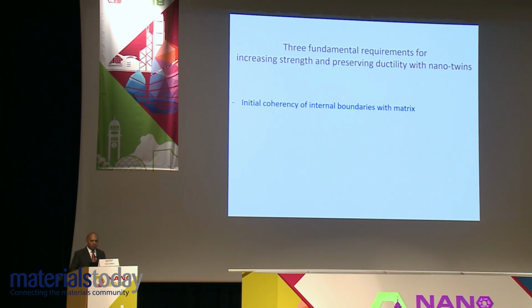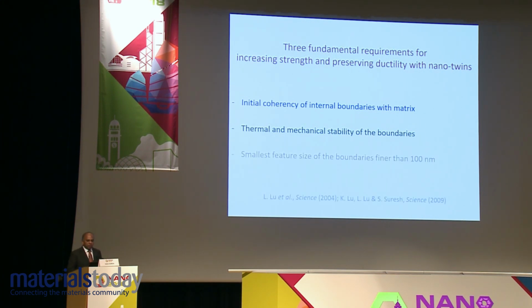What are the requirements? We identified 3 requirements. You need to create internal boundaries that at least have initial coherency, mechanical coherency with the surrounding matrix. You need to have thermal and mechanical stability of the boundaries during mechanical loading, whether it's monotonic loading or cyclic loading, at room temperature or at elevated temperatures. And then in addition to that, there is something unique about the nanoscale, things that you don't see at the micro scale. At the nanoscale, if the internal boundary feature size is typically finer than 100 nanometers, then you have an opportunity, if all 3 conditions are satisfied, at least in theory, to create a structure that has increased strength and it has the potential for reasonable ductility.